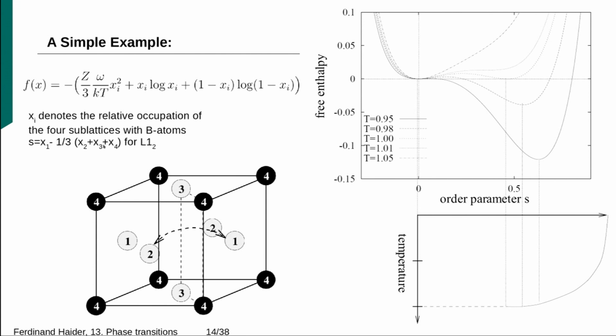And if you choose this phase here, you can plot this as a function of the order parameter. At high temperature, you have this single minimum at order 0, so all the B atoms are equally distributed among the lattice sites here. If you lower the temperature - this is very high temperature, 5% above the critical temperature. Here at 1% above the critical temperature, you see that such a side minimum is developing here. Precisely at the critical temperature, you have this minimum here, and still the other minimum here.